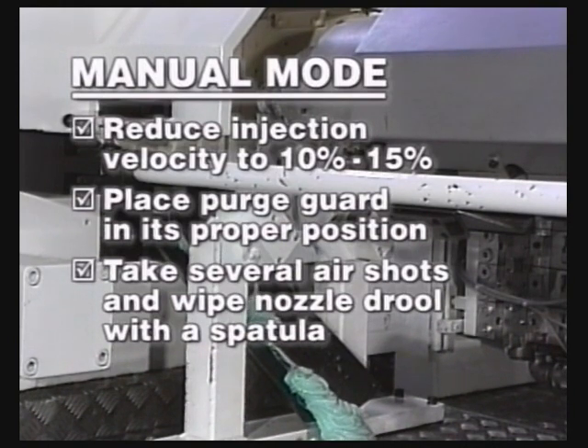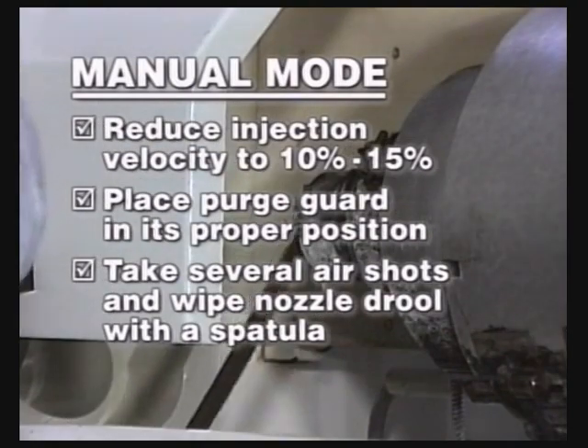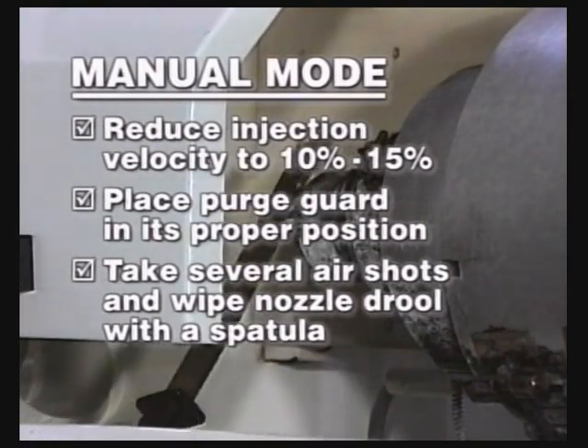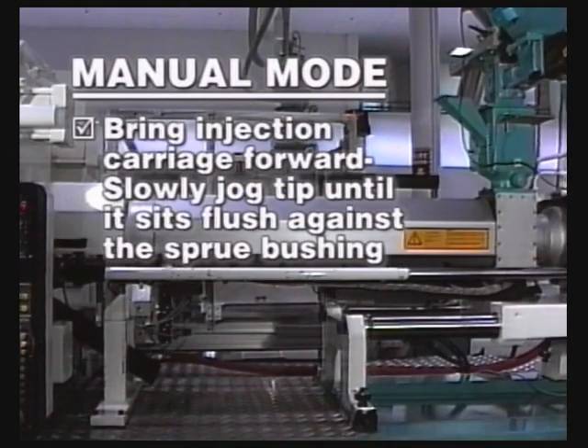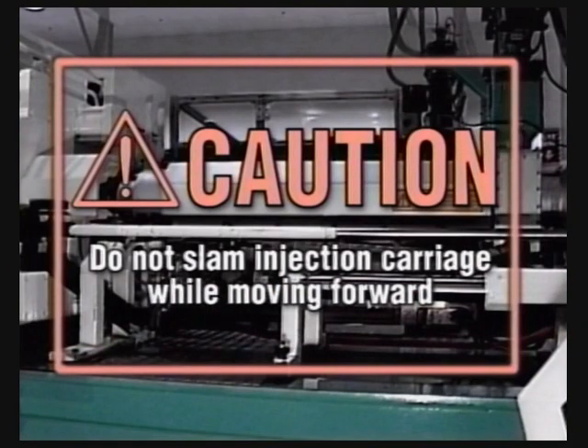reduce the injection velocity to 10 or 15%. Take several air shots and wipe the nozzle drool with a spatula. Bring the injection carriage forward and slowly jog the tip until it sits flush against the sprue bushing. Be careful not to slam the carriage, as damage to the nozzle tip or sprue bushing may occur.